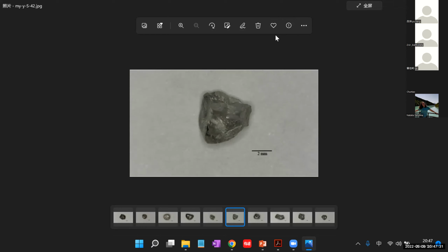those that people suspect are not coming from the deep, but coming from during the crystallization of eruption of kimberlite. So some of the diamonds will form in that process. And also they could be formed by fluids, and let's say not in a typical environment we are thinking about for crystallizing those big crystal diamonds. So those could be very weird conditions that could also lead to something similar to this, at least a current argument by Walter et al. So okay.